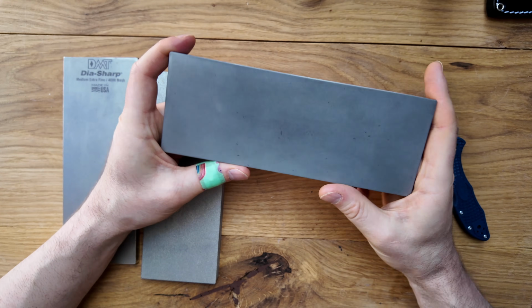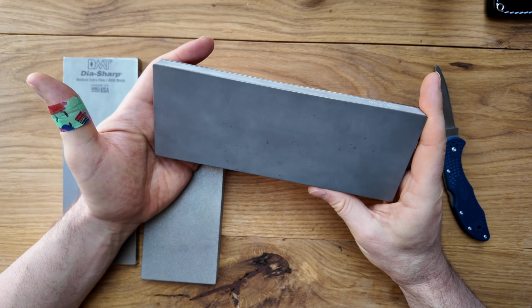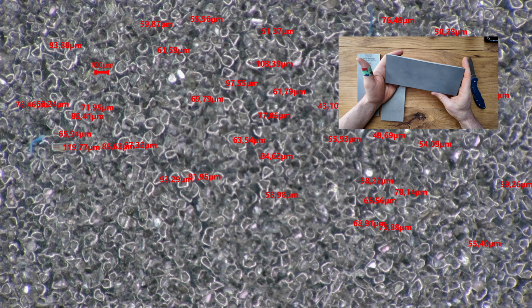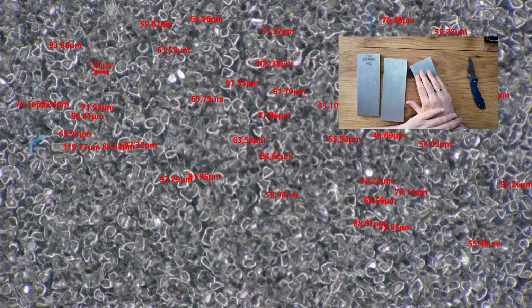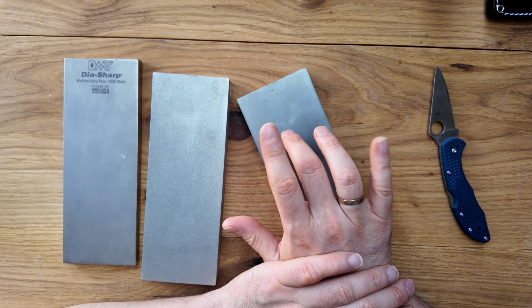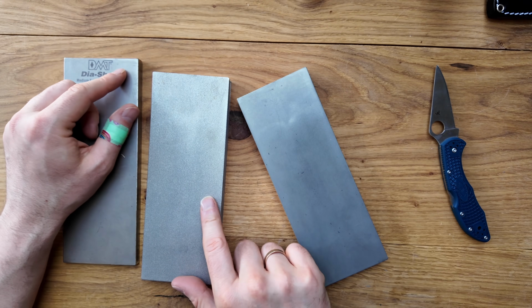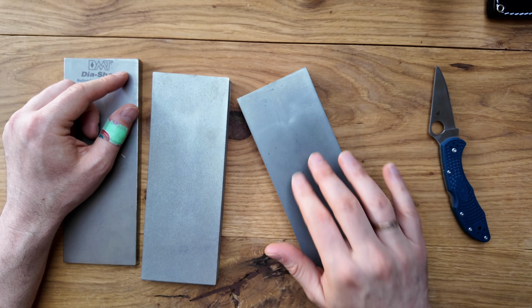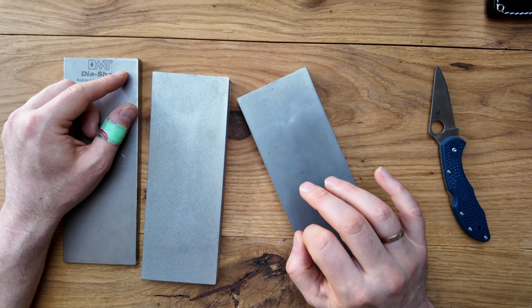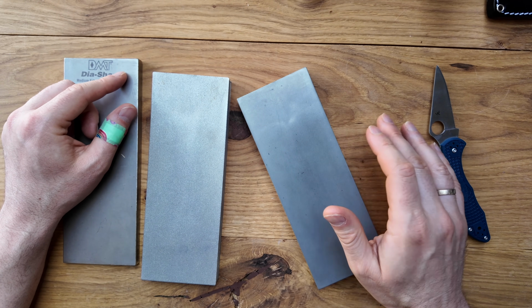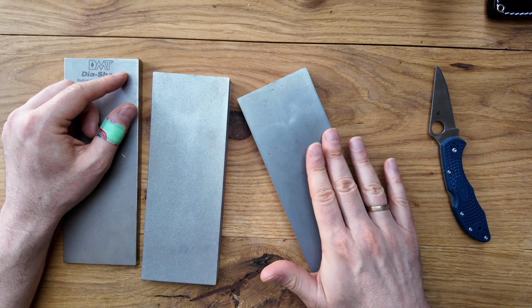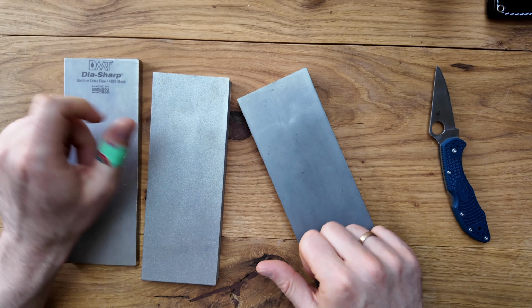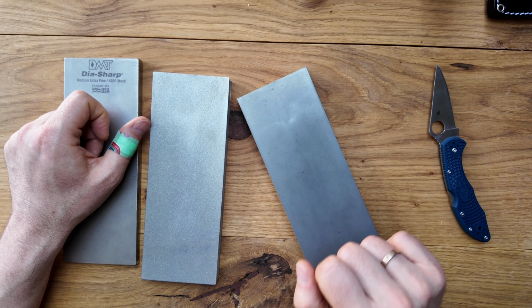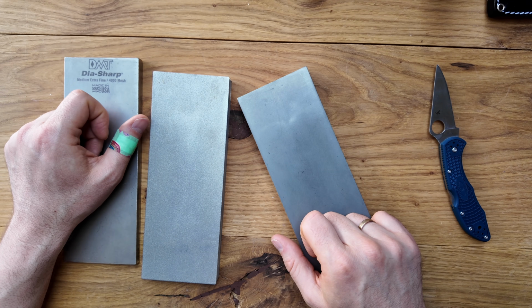So for 325 grit, the normal micron size of the grains would be 44 to 45 microns. So only one of the measurements lands near the 44 micron mark. The bulk of the grains sit at 55 to 85 microns. So the same pattern as the 220. The stone is roughly running 1 grade coarser than rated. These grain sizes are more consistent with the 220 grit stone. So the 325 Sharpal is also not what the label says it is.